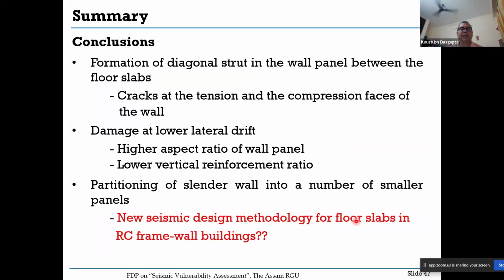Fine. So to summarize, you have the formation of a diagonal strut in the wall panel between the floor slabs. As we can see, the cracks on the tension phase and the crushing in the compression phase have all formed. Then you have damage at the lower drift level, which depends on the aspect ratio, a higher aspect ratio of wall panel, and a lower vertical reinforcement ratio. And all these, whatever I have shown you, are part of the possible beginning of a new seismic design methodology for floor slab.